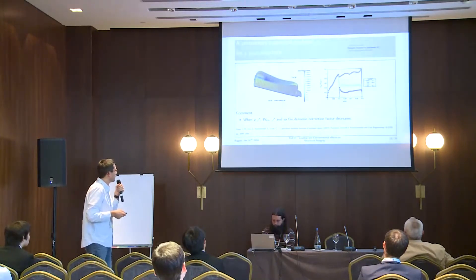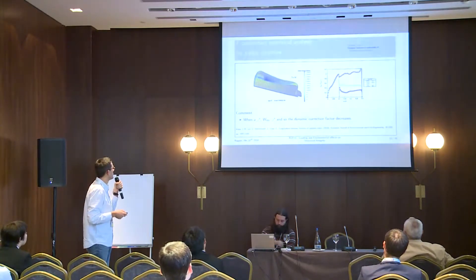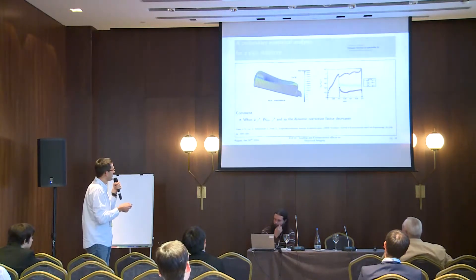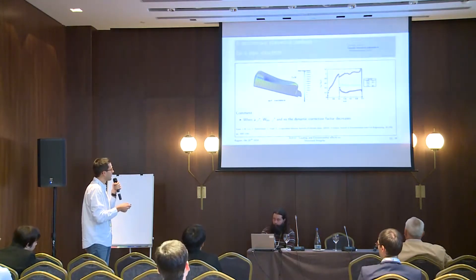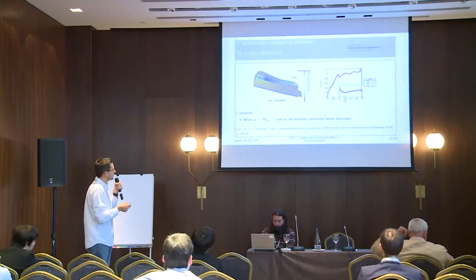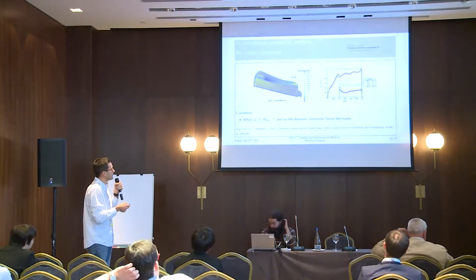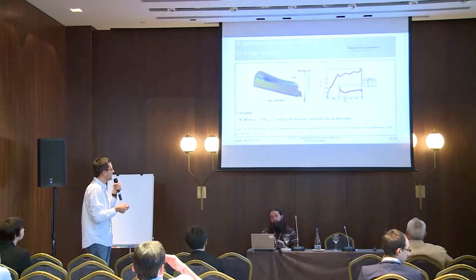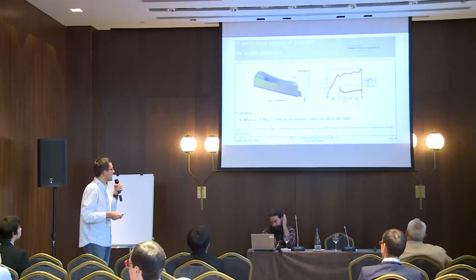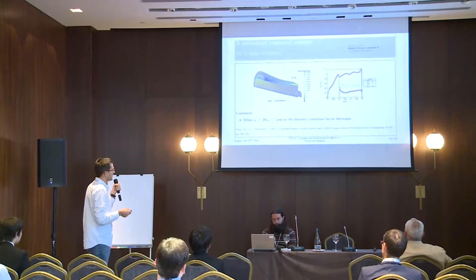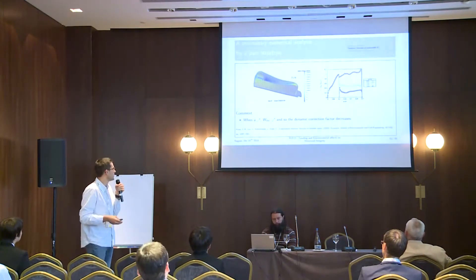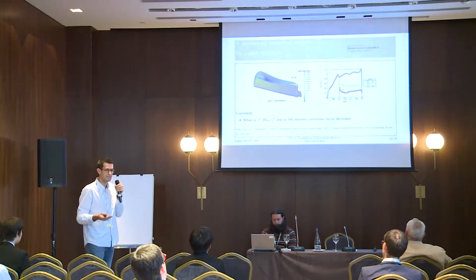As an example with the pipe structure, this preliminary numerical analysis shows the evolution of the dynamic correction factor as a function of crack length and crack velocity. We can observe that during the dynamic regime of propagation, the plateau value decreases strongly as a function of crack tip velocity. In that case, the dynamic correction factor decreases with increasing crack tip velocity.